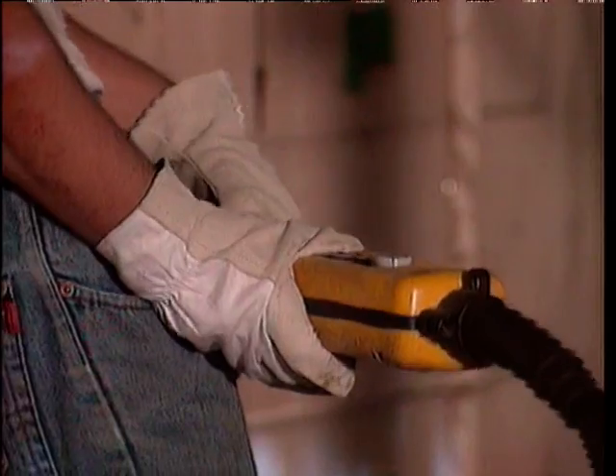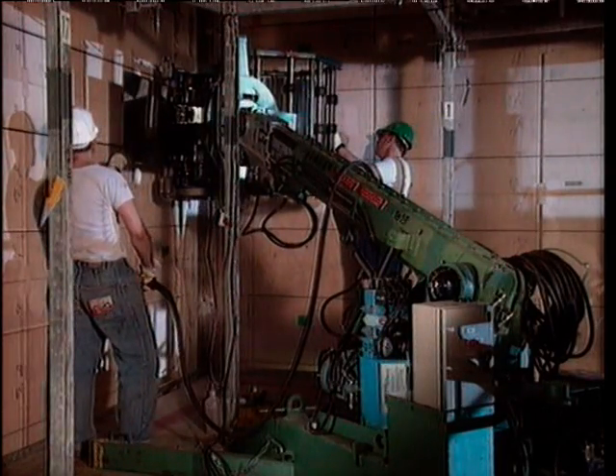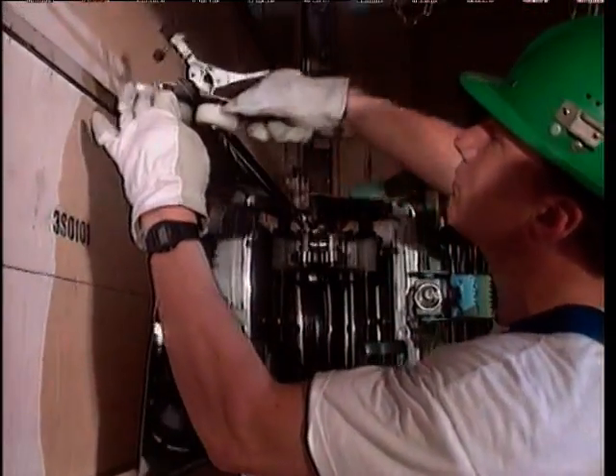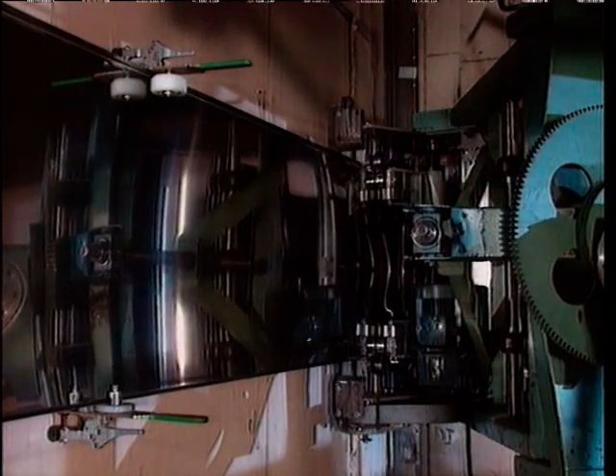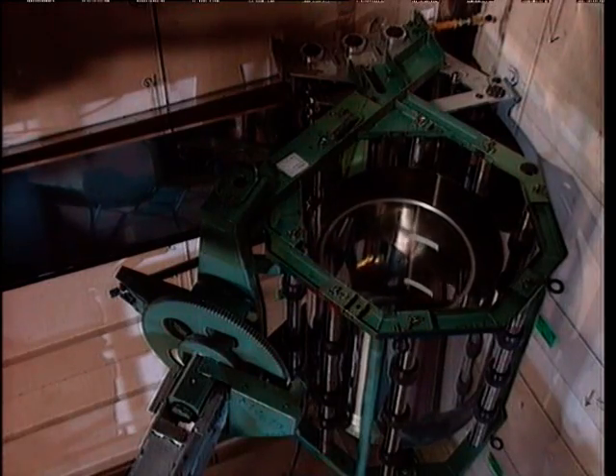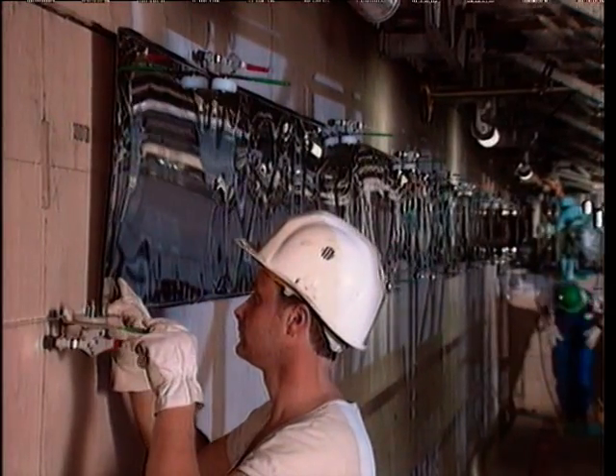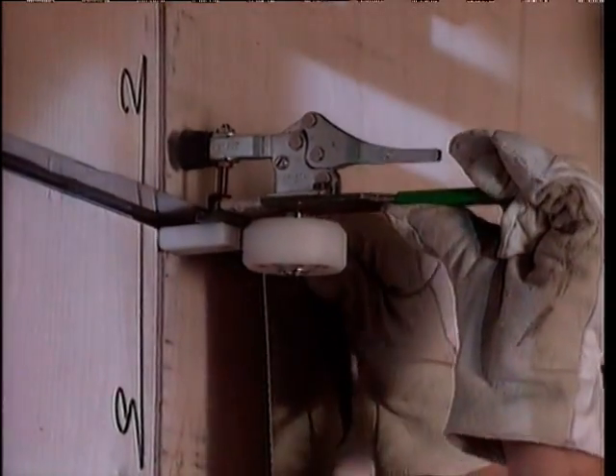The tongues guide the positioning of the secondary membrane strakes. As for the tongues, Invar strips, 7/10 of a millimeter thick, are delivered in coils which are automatically and continuously unreeled and unwound along the length and width of the tanks. When the Invar strips come off the reel, the edges are folded and lifted up at a right angle to make 500 mm wide strakes. These fit perfectly between the two adjacent tongues, equipped with temporary guides to make the unwinding easier.